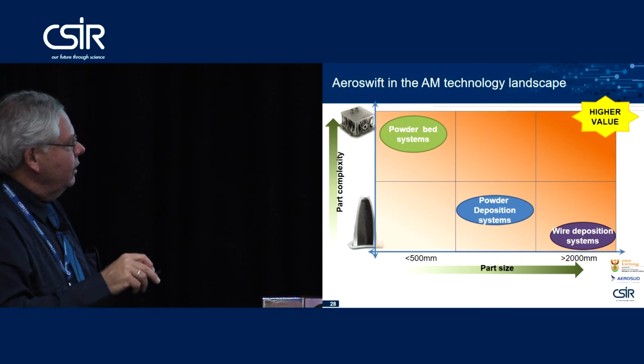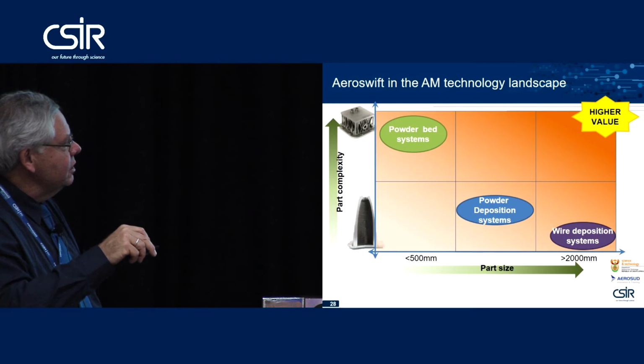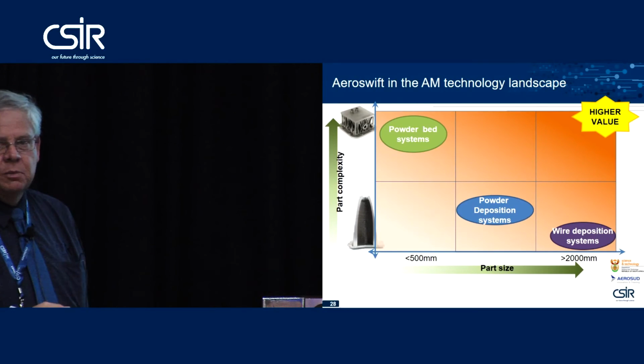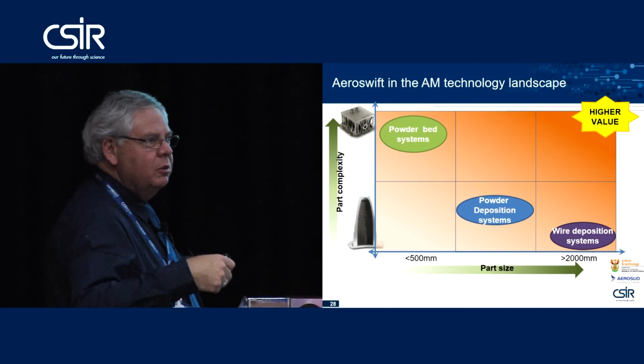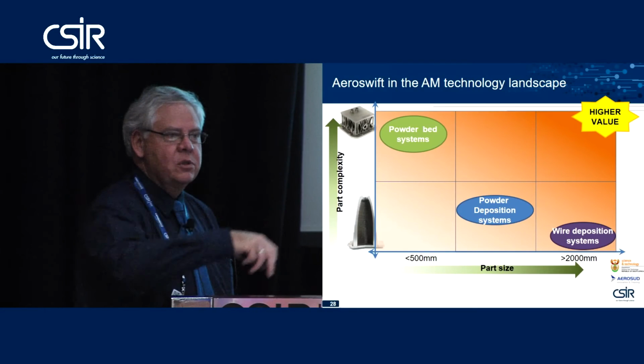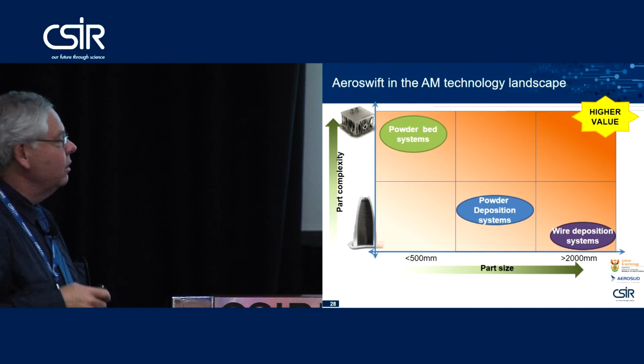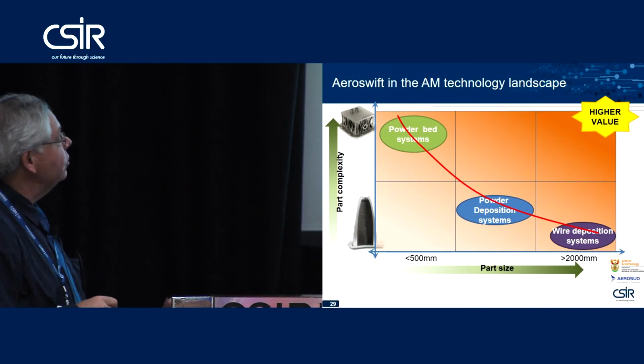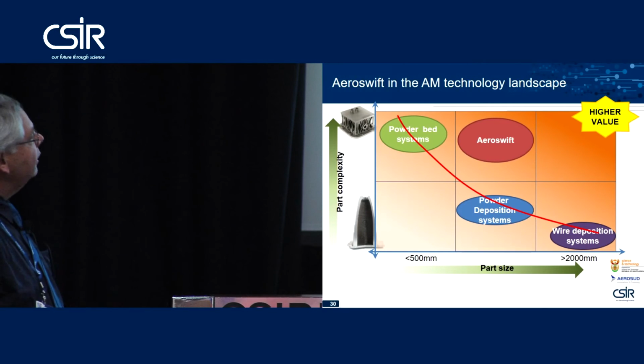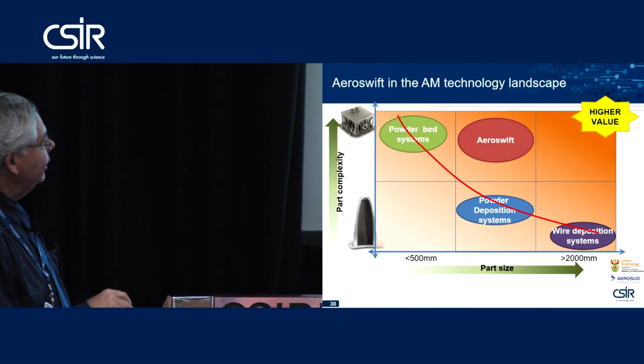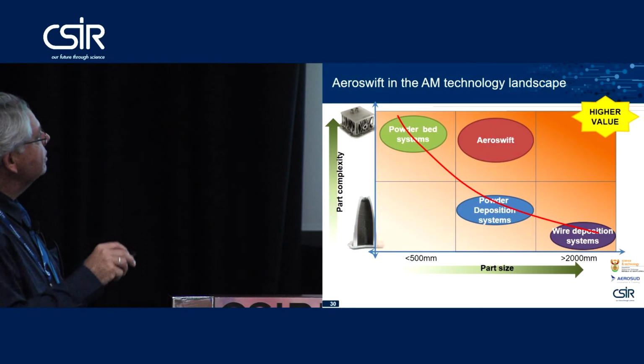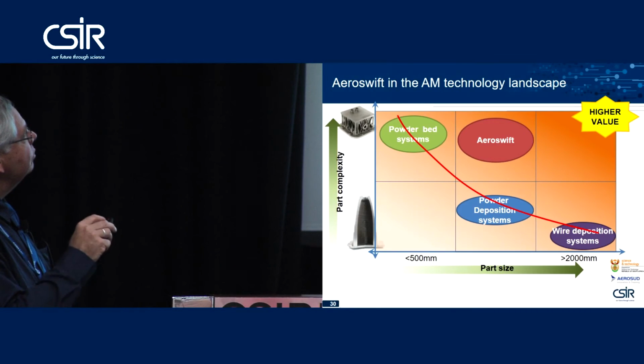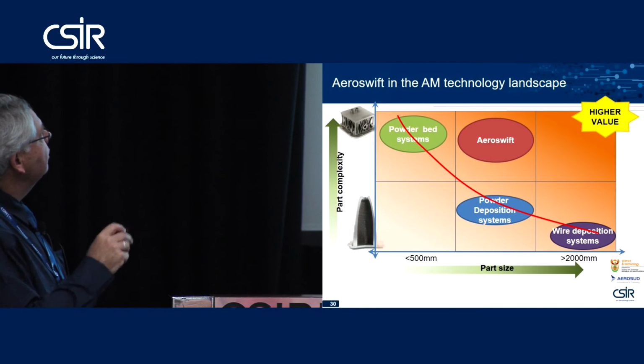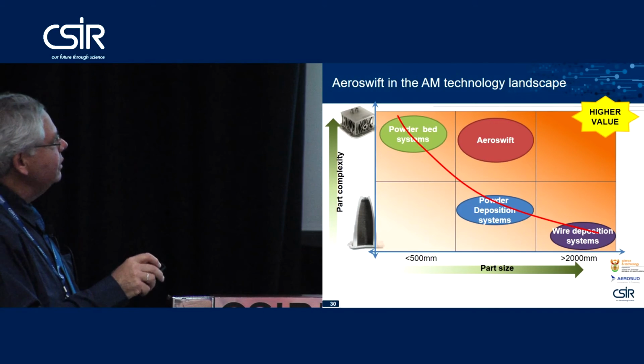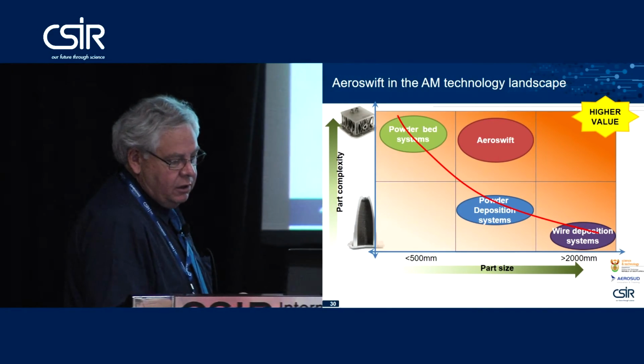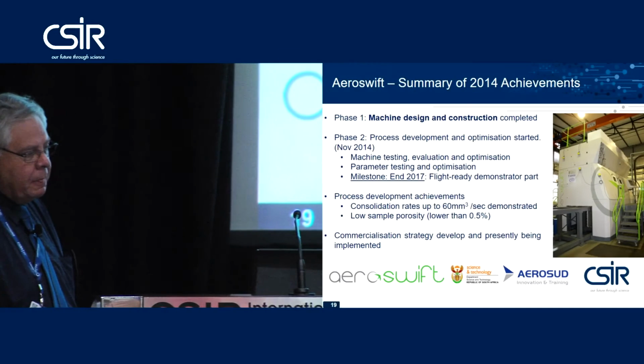And then one can go to very, very large systems where you actually move away from laser-based processes, but use a welding process, combining it with wire and depositing large structures. Aeroswift falls in this domain where we have already significantly larger part size, but also the potential for highly complex components, and obviously you want to sit in that top right-hand quadrant to get high value components.